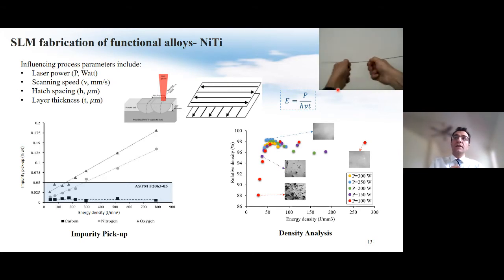One major challenge with optimization of processing parameters for additive manufacturing of nitinol is that we need to make sure the material would show superelasticity right after the fabrication without requiring any heat treatment or post-processing. Before this work that I'm gonna talk about, the highest achieved superelasticity in the literature for the as-fabricated part was only 2%.